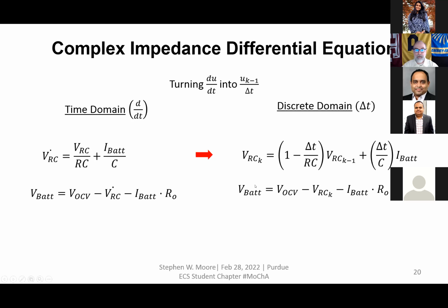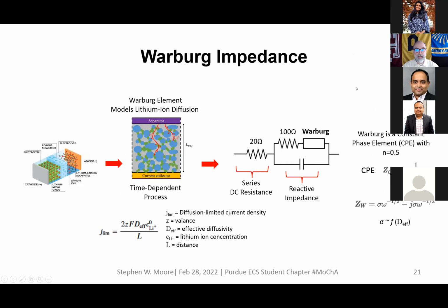However, there's always another level of difficulty whenever there's modeling. So the next level of difficulty is the Warburg impedance. And if you're not familiar with this term, this is something that you can Wikipedia and you can find out what Warburg impedance is, or you can simply look over here. For those people who are familiar working in the complex frequency space, a Warburg is simply a constant phase element. And it's a constant phase element with its coefficient equal to 0.5. Or in other words, it's a 45-degree angle on the Nyquist plot.